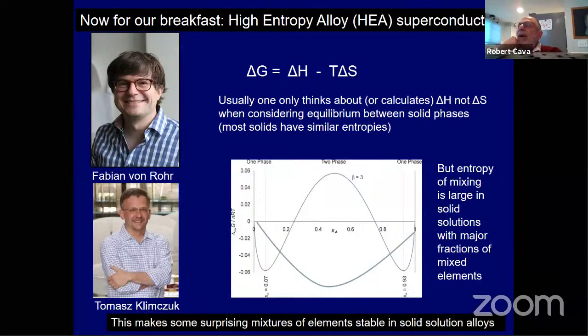The interesting thing to me about high entropy alloys is that, normally, everybody knows that the free energy of formation for any substance depends on an enthalpy term and an entropy term. But most often, the entropy term is not even calculated, because in most substances the entropy comes from lattice vibrations, which are all about the same. So basically, it doesn't have that much of an impact. Or, you can calculate delta H, but it's hard to calculate delta S. And DFT calculations calculate delta H at T equals 0, so there's no delta S term.